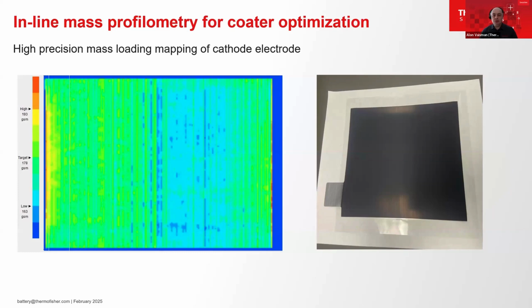Being able to analyze the distribution of active material on the entire electrode as it is being coated gives one the ability to make quick adjustments and tune the coating process on the fly. The example here shows a variation in loading between the left and right sides of the patch. You can also see small vertical streaks that are actually visible in the photo of the same patch on the right, if you look closely at the light reflection on the top and bottom of the central area. With this information available on the fly, the ability to tune the process as it is running is valuable, and it helps speed up parameterization and validation workflows.